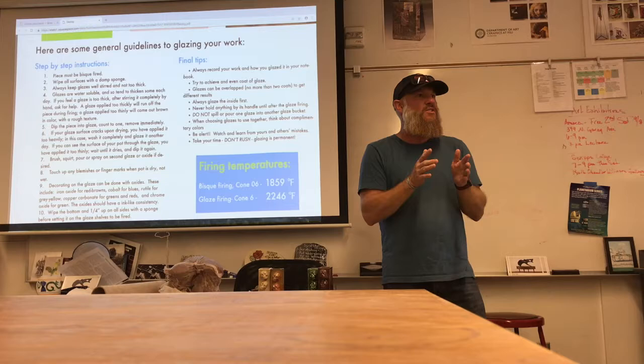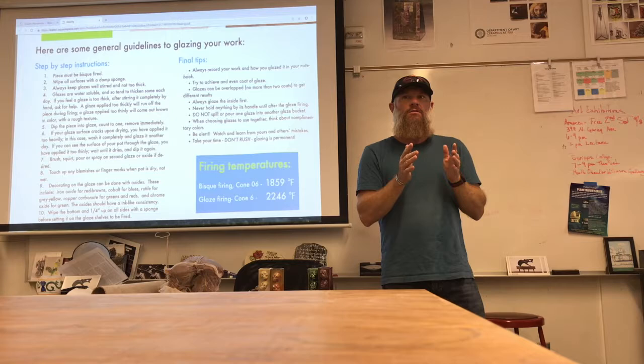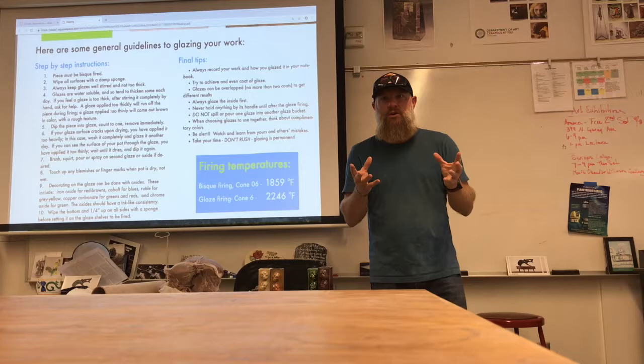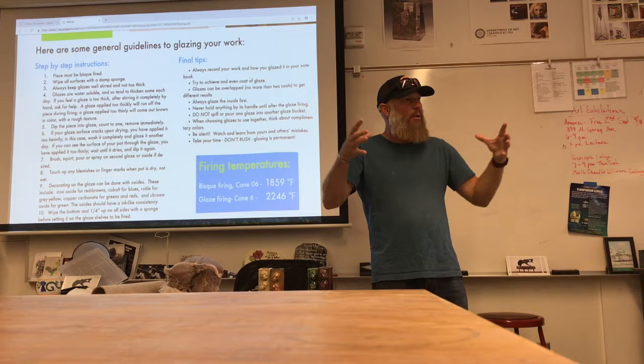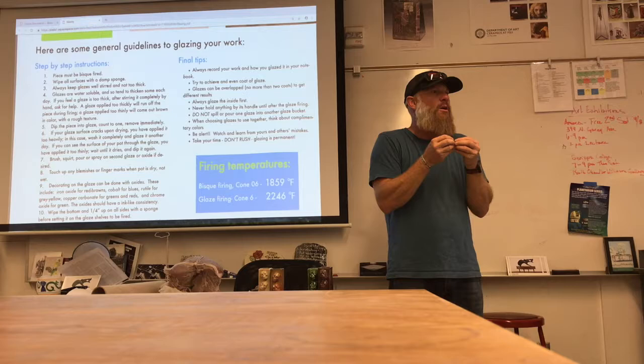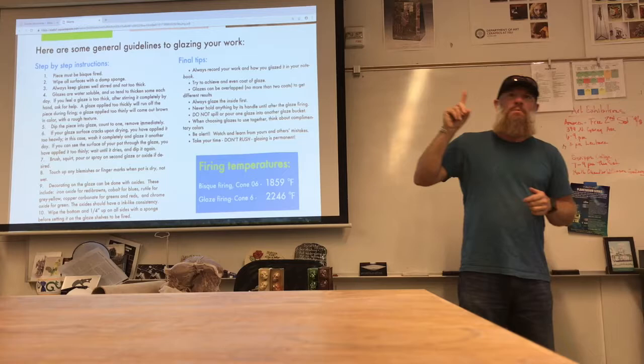We keep it low at 180 degrees because it's well below 212 degrees. At 212 degrees, water boils. When it boils, it puts off steam. When the steam comes out of the clay, that's what causes pieces to blow up in the kiln. If there's an air pocket, that can also happen — it's a chamber where fumes from off-gassing or steam cause those explosions in the air bubbles.